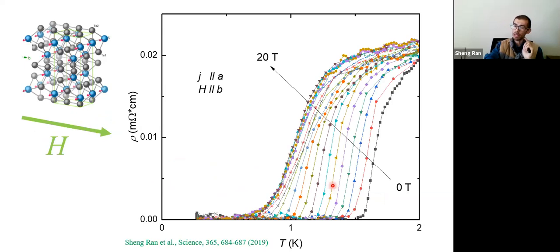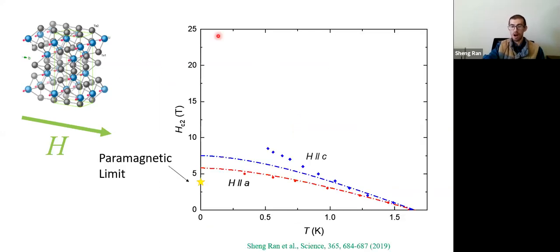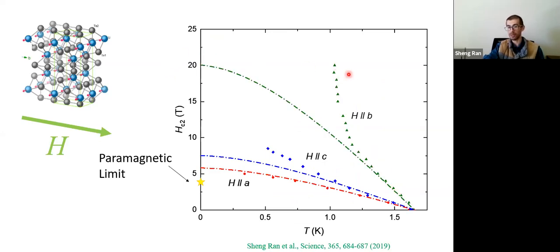This is what happened if we apply the magnetic field along the b-axis. First, we can see even at 20 Tesla, this is still a superconducting compound. So actually, by 20 Tesla, it's only enough to suppress superconductivity from 1.6 K to 1 K. So this is a super large critical field. Now, if we plot on the same plot, 20 Tesla is here. It significantly deviates from the orbital effect. Well, 20 Tesla was already the maximum field we can apply in the lab.